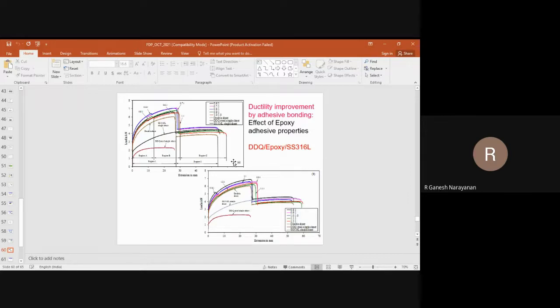Yes. So now this adhesive bonding also has got inherent flexibility to change its overall deformation behavior. One example is properties of adhesive. It is a sandwich material only, but the core layer is made of adhesive itself, like that. And if you can see this example, it is deep drawing quality steel bonded with stainless steel using epoxy adhesive. And you can change epoxy adhesive properties by changing its resin to hardener ratio. And by doing that, you will see this is a typical load extension graph. You can see there is a tremendous change in the ductility and load requirements. So you can basically manipulate the stress strain behavior, manipulate the final forming behavior, deformation behavior by changing the core properties, keeping the thickness constant.